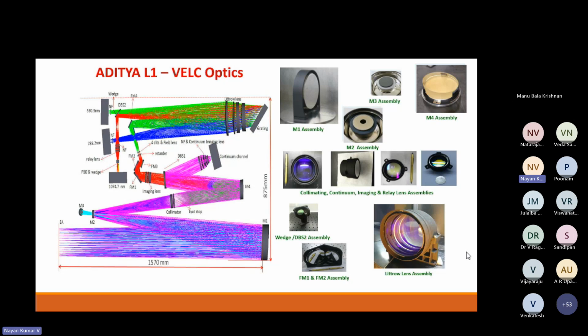So these are the assemblies which were realized. We had a variety of optics. One is this Zerodur-based low roughness mirror, and coating is a very important aspect here. You may achieve a polished surface, but upon coating it may get degraded. So for that also we developed some special processes, how to clean this and then get this coating without any spatter over the 200 mm.